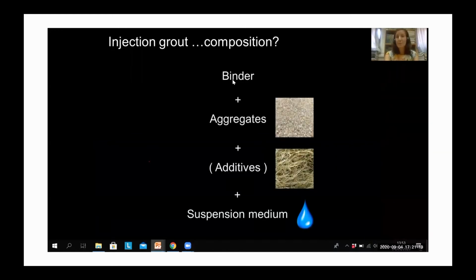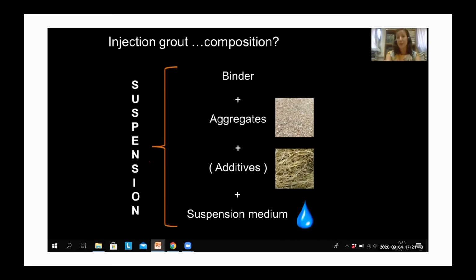So what's the composition of an injection grout? We always have a binder, which is binding everything together. We can have aggregates of different types, of different granulometry. We'll see this later in more detail. We may have additives, not always, not necessarily. As we'll see, it's really according to our needs. And we always have a suspension medium, which is typically water. It's a liquid which keeps all these components in suspension. And I underline it's a suspension, because we might be led to think it's a solution, but actually, no, we're talking about a suspension. So we have particles, aggregates, and binder particles suspended in this liquid.